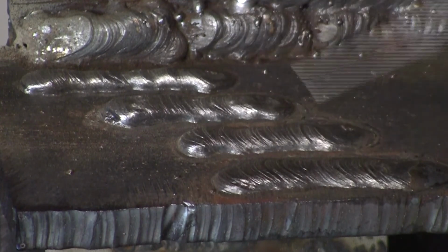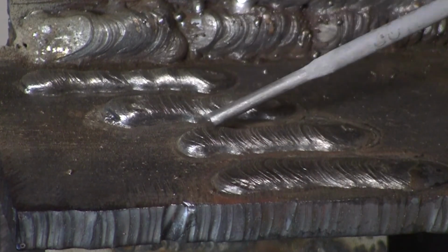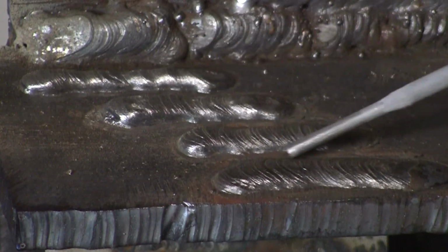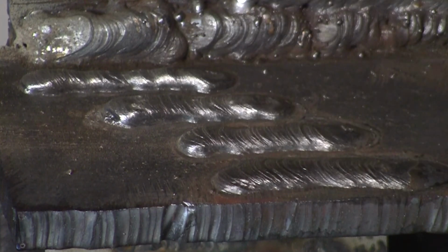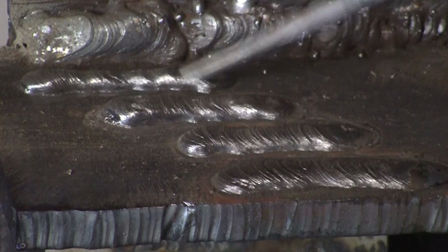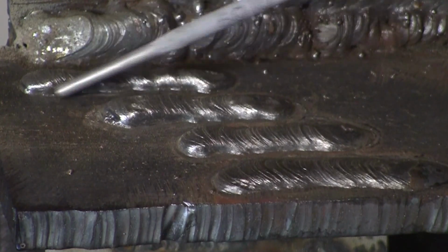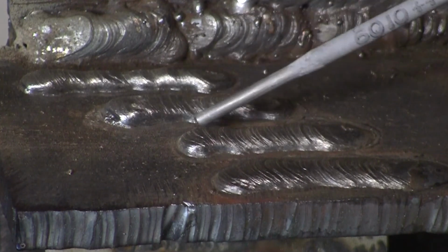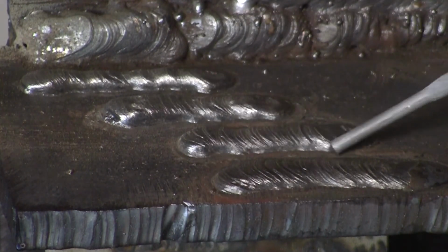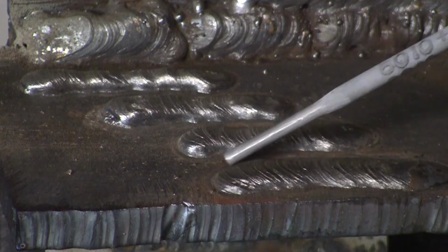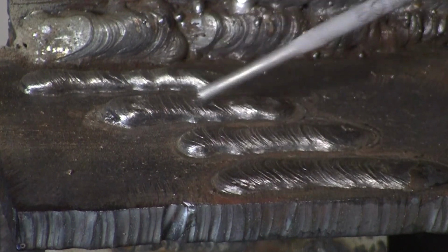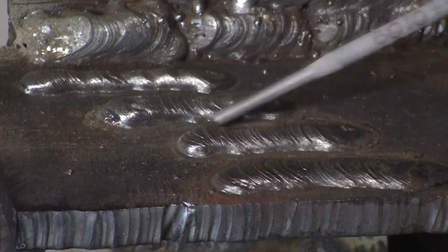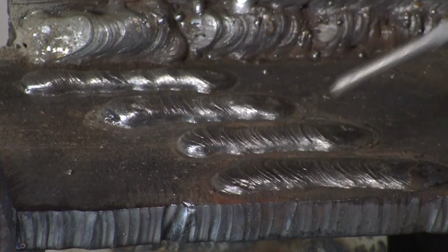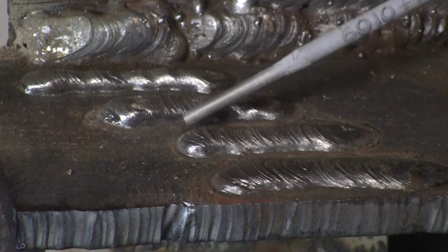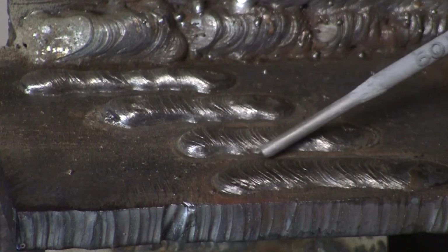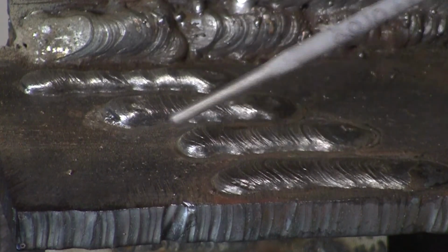These are the four welds I just did, 70 amps, 80 amps, 90 amps, 100 amps. So right out of the box, you can see the 200i is doing just what it's supposed to do. You can see how at 70 amps, we're kind of cold, we're balling up, we're not getting a lot of penetration into the plate. 80, a little bit more, 90, starting to sit down a little bit, penetrating a little deeper into the metal. 100 amps, we're starting to bite in pretty well. So with a little amperage adjustment, you can see the different characteristics of each weld and how the higher amperage creates a hotter weld that penetrates more into the plate.